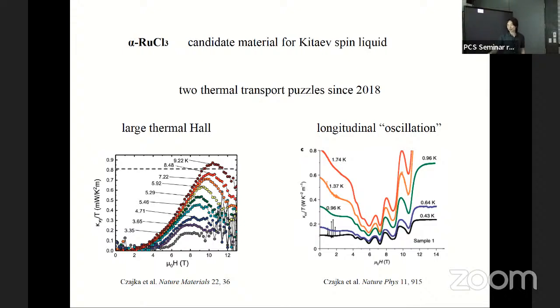If you tune the magnetic field, you see the longitudinal thermal transport has a very obvious oscillation between, say, 0.4 Kelvin and 4 Kelvin. Above 4 Kelvin, it goes away. But at very low temperature, it has this very obvious feature. This certainly is very strange and needs some explanation.